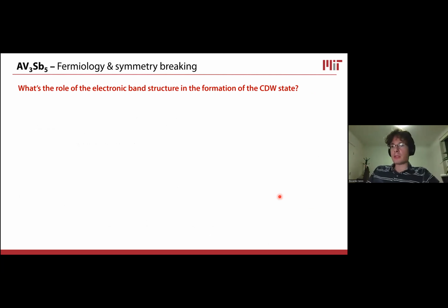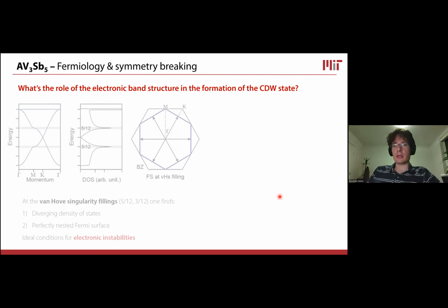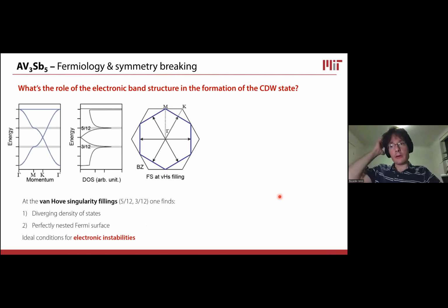So the question that we asked ourselves is, what's the role of the electronic band structure in the formation of the charge density wave state? If we focus on a different part of the electronic band structure, specifically the Van Hove singularities, what happens if you tune your Fermi energy to one of the two Van Hove singularities in the band structure of the 2D Kagome lattice? What you see is that the Fermi surface is perfectly nested in the limit of nearest neighbor hopping only.